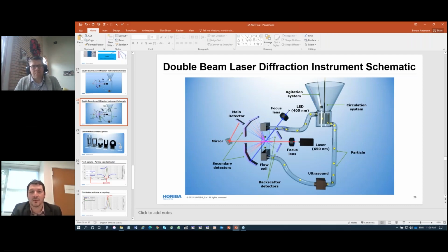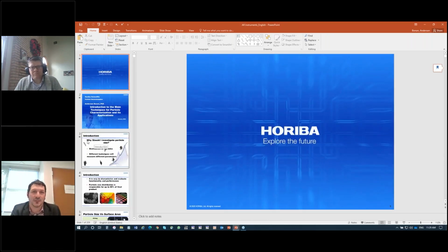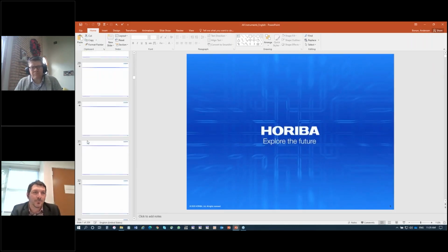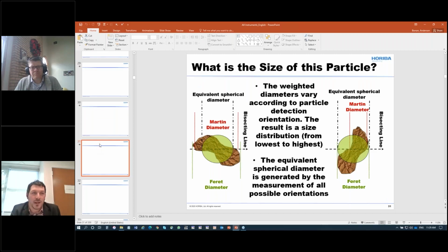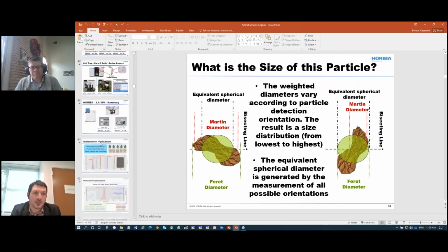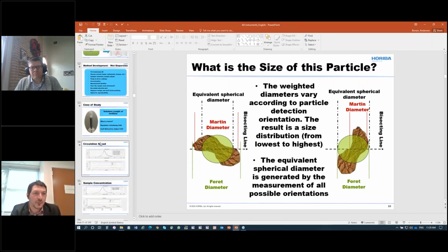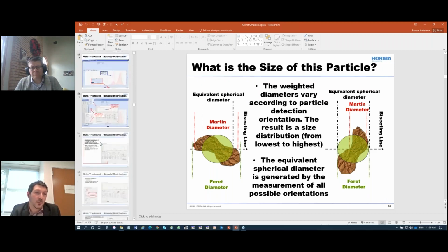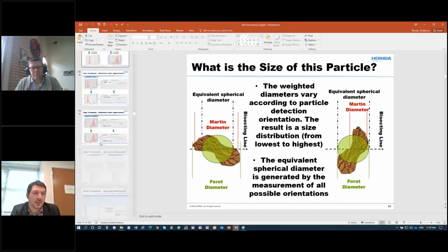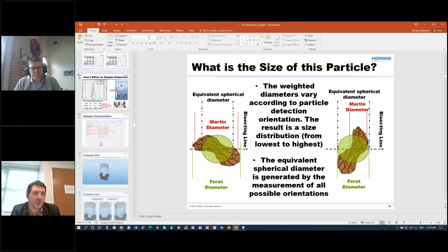You see if it forms agglomerates, if it sedimentates, or if the particles keep swimming on the surface, so you can see what happens with the particles. So you definitely want to do this test before you put the sample into the analyzer. And then if you have a decent dispersion, you can go ahead and measure and compare results in different mediums, which is exactly what I'm looking to show here.